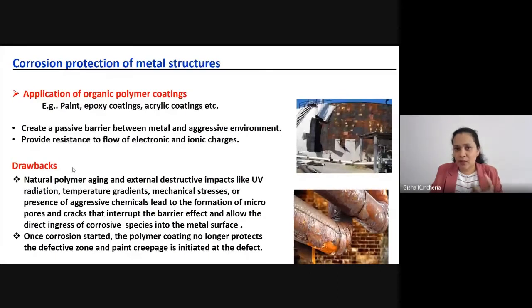These defects, human eyes couldn't detect. But when such a defect is formed, these corrosive agents pass through these defects and reach the metal surface beneath the coating, and corrosion starts. Once corrosion starts, these polymer coatings are no longer able to give any protection. Slowly the corrosion will propagate and spread through the metal surface.